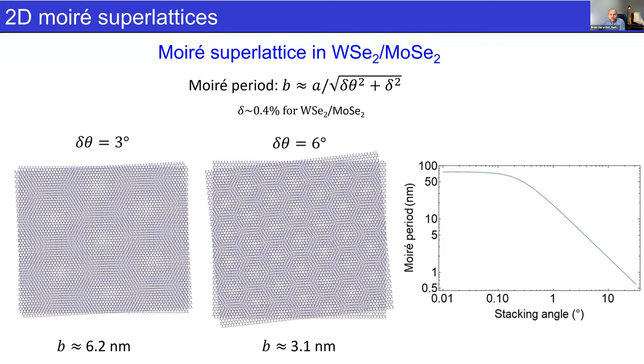So for our structures, there's a very small lattice mismatch, primarily because we have the same chalcogen atom. If you switch the chalcogen atoms, for instance, to replace one of these with sulfur, then you end up with a much larger lattice mismatch, on the order of 4 or 5%. And so obviously your periodicity goes down. So anyways, the nice thing is we can really engineer these features.